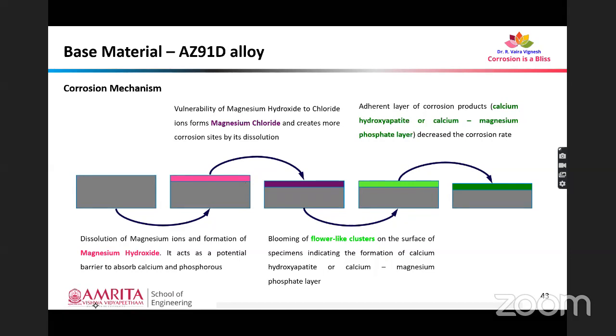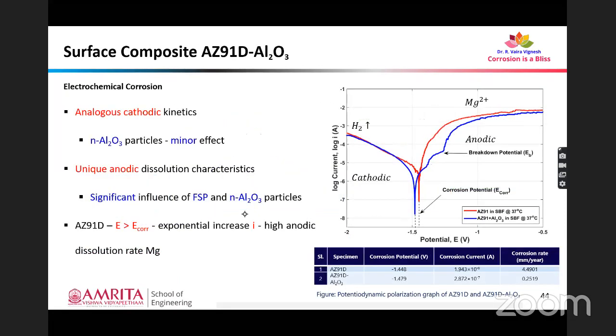Since we have brought down the corrosion rate to less than 0.5 mm per year, this is also a good sign for the material to be an effective biodegradable implant. Yes. And coming towards the electrochemical corrosion analysis.